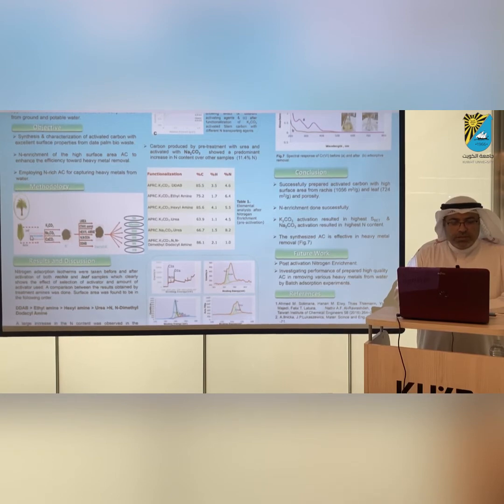We heat it at 600 degrees, and then we obtain what we call the carbonized carbon. Of course, this does not have a high surface area, so we have to activate it with chemicals. We have used potassium carbonate. We also tested sodium carbonate, calcium carbonate, and other chemicals like potassium hydroxide. But we found that potassium carbonate, the first one, gives us the highest surface area. It's very helpful in generating porosity in the material.